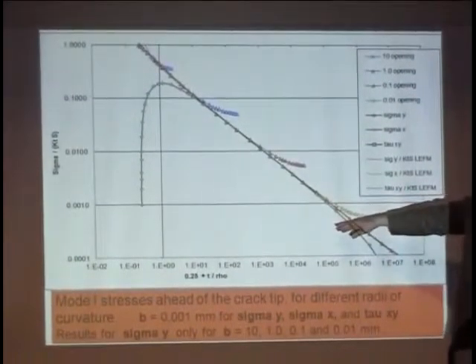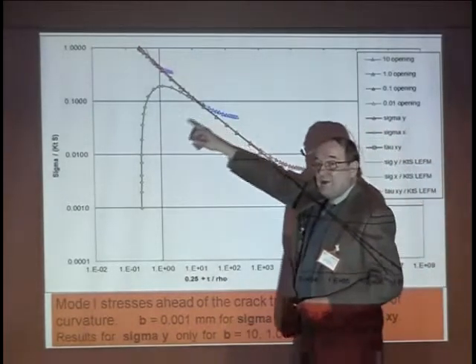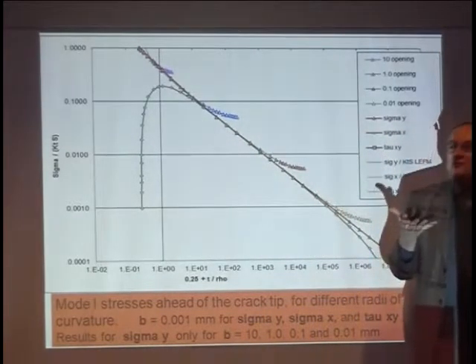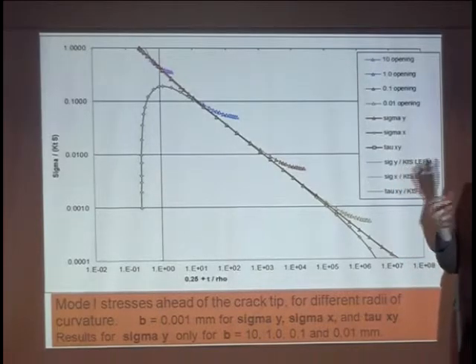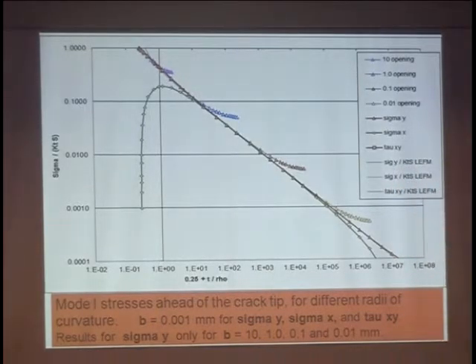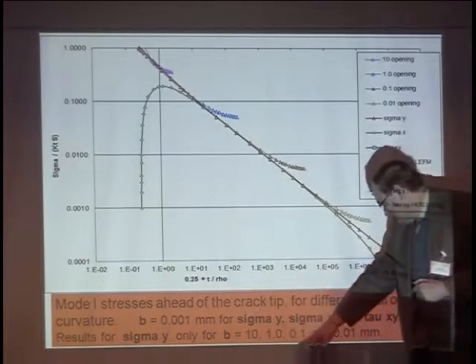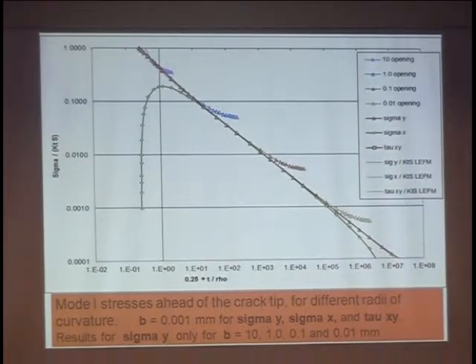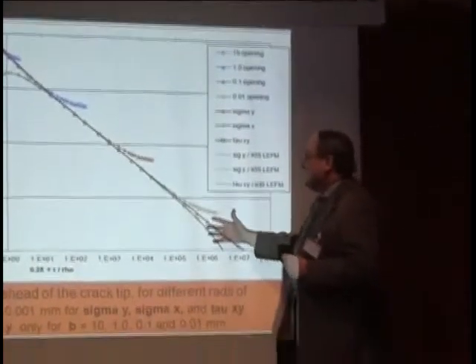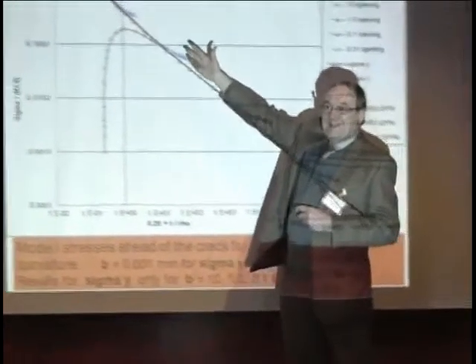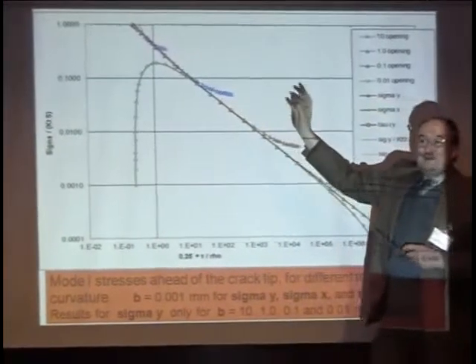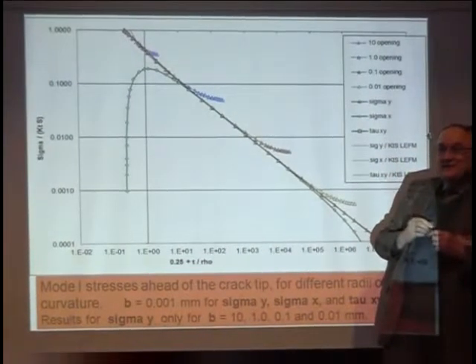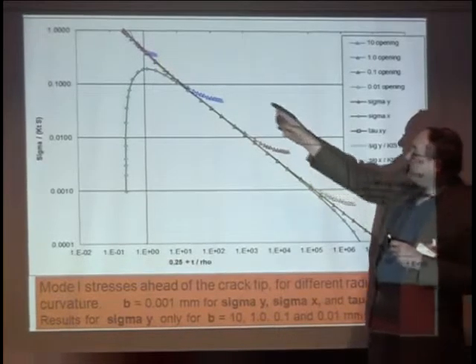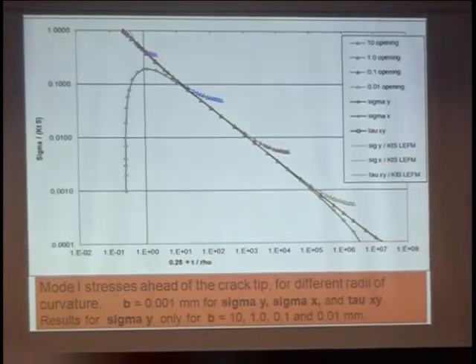But when I'm very close to the crack tip, because of the shape of the crack tip, the notch shields you from the influence of the T-stress. But more importantly, with these particular dimensions, my stress concentration factor is 20,000. Rather big. So if I put in a T-stress, I've got to go up to a factor of 20,000 to get up to here, times that. So I suppose it is there, but you just can't see it, it's minute. You would only see it really with, for example, a circular notch, which is really what we're looking at.